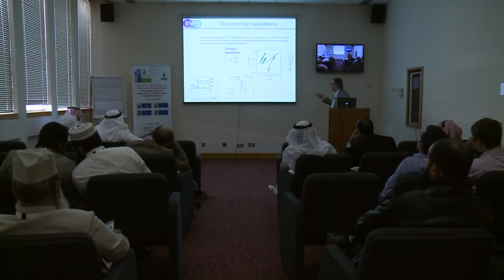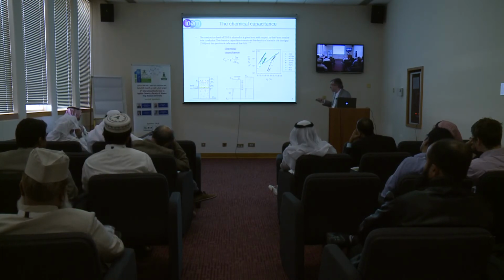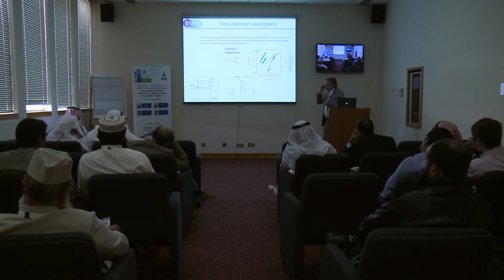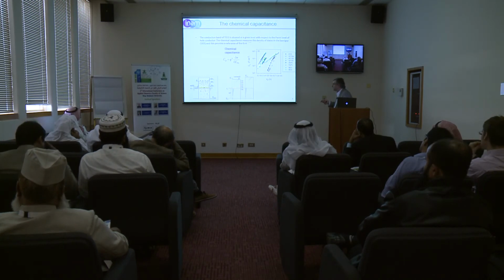Okay, so you see this is the voltage, and this is exponential scale, so this is really a totally exponential plot of the density of states of electrons in titanium dioxide. This is the conduction band. That's very important because that is where the dye injects. We cannot get up there. But we can see something very important, which is a shift with respect to energy levels in the electrolyte.